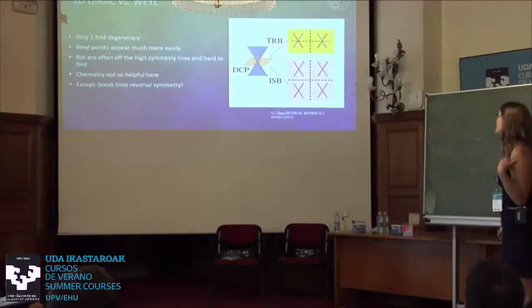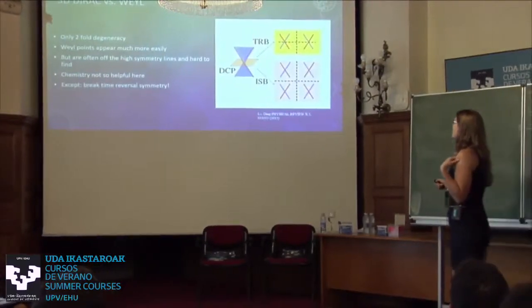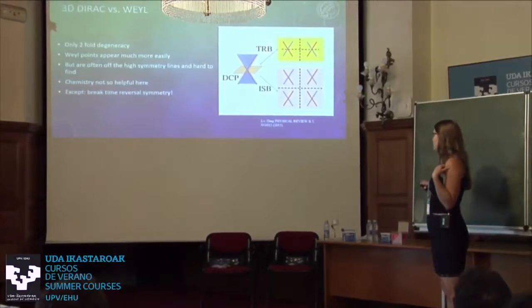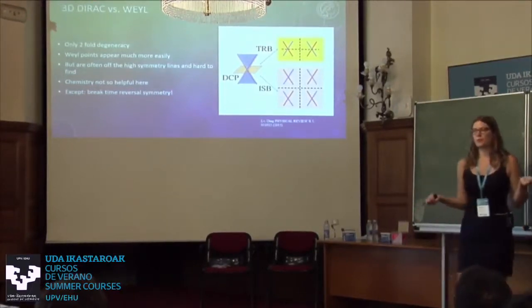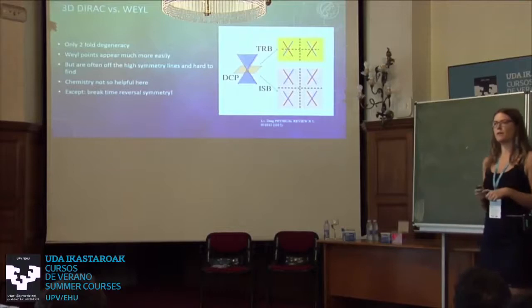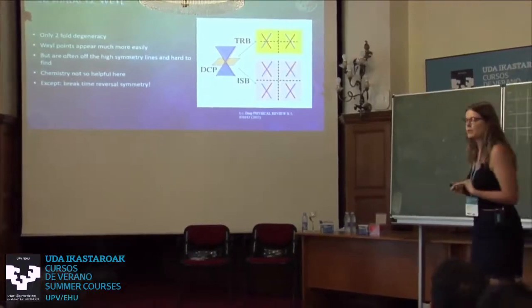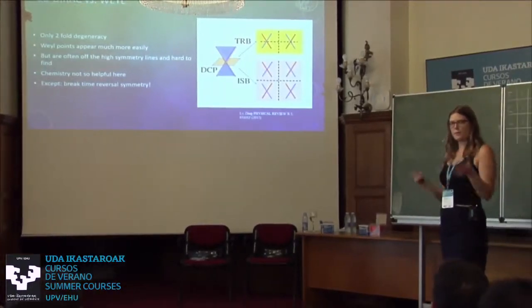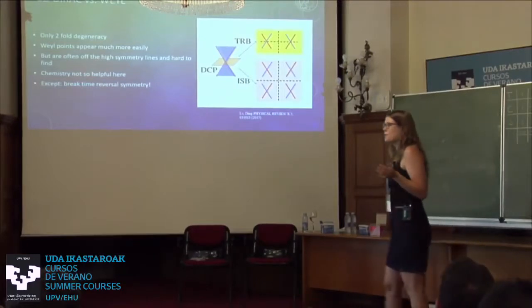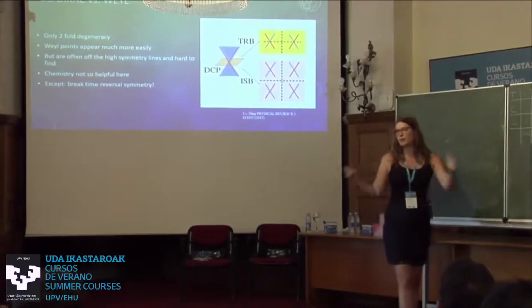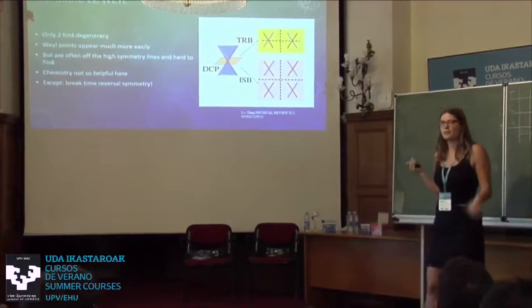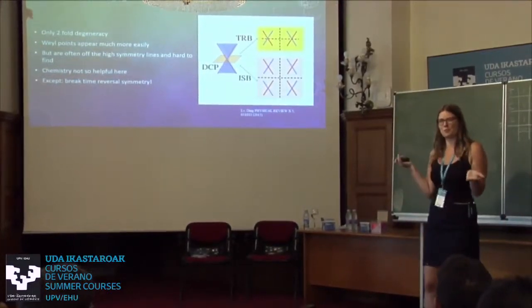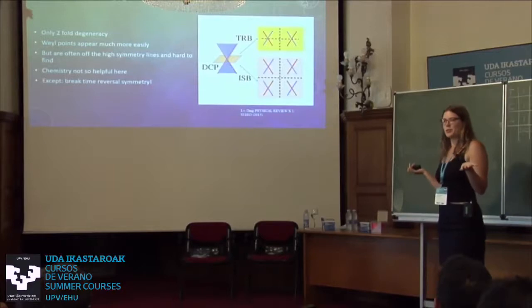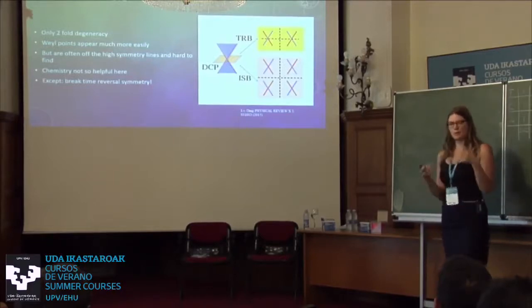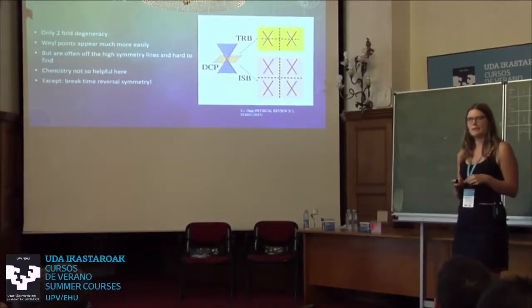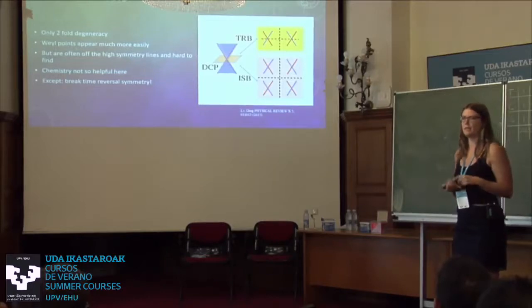Okay, so Weyl semimetals is a problem where, instead of a fourfold degeneracy, you have a twofold degeneracy, and you get that usually by breaking either inversion symmetry or time reversal symmetry in your fourfold degenerate system. The problem is if you have an inversion asymmetric system, you often have those crossings away from high symmetry lines, so we cannot really use the concept we use for 3D Dirac semimetals anymore. So looking for Weyl semimetals in inversion asymmetric compounds is really messy, and chemistry doesn't really help us, sadly.